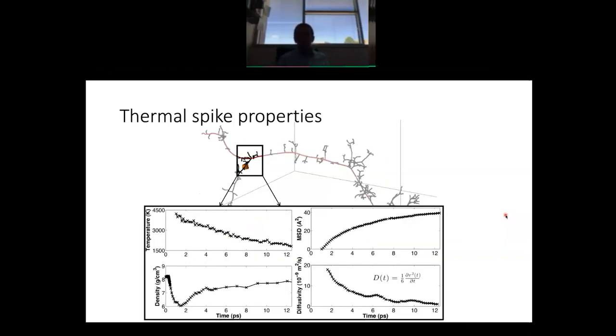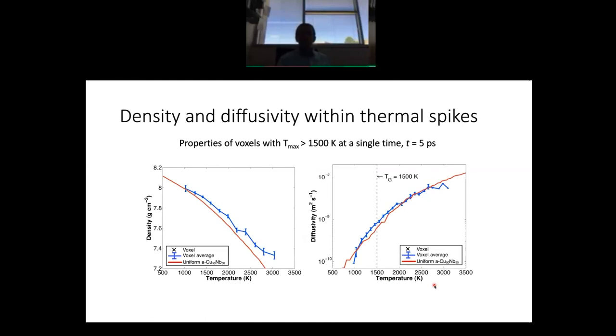We can then look into individual thermal spikes and see, for example, how quickly the temperature changed as a function of time. Here's a plot of temperature versus time. The x-axis here is time in picoseconds. From this, we can derive quench rates. We can look at how the density changed. We can look at how the mean square displacement of the atoms changed. As a result of that, we also know the diffusivity. And we can start to see what is the state of the material at the end.